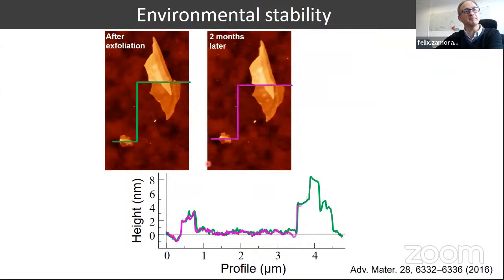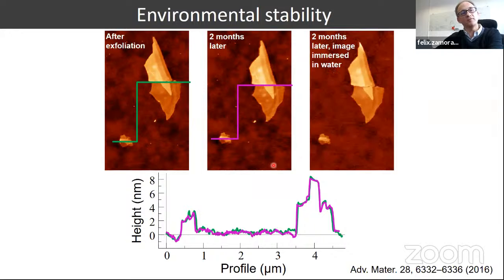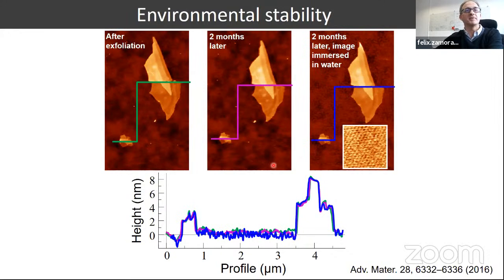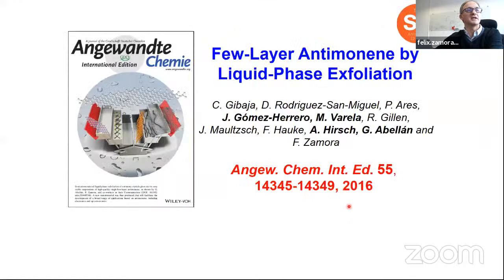And then we took again the height profile, and we observed that nothing changed. And then we immersed this substrate into water, and we remeasured the height profile, and we observed no change, confirming that we have a nice environmental stability. In addition, we were able to have atomic resolution on the top of our layers. So this was the first approach to isolate few and single layers of antimony.